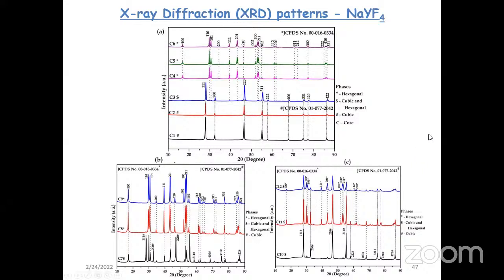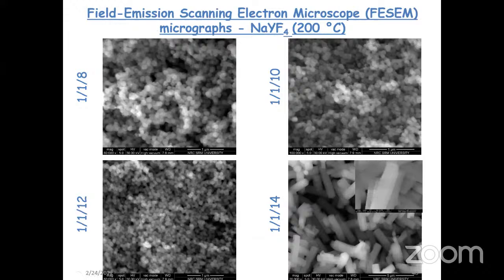The prepared core materials were subjected to XRD analysis. From the pattern, we were able to identify whether the molecules were cubic, hexagonal, or a mix of cubic and hexagonal. These are some pictures of the different ratios of yttrium nitrate and sodium fluoride. You can see that a very clear cubic or sphere-like structure is formed at 200 degrees Celsius. At 180 and 160, there are hexagonal systems also.